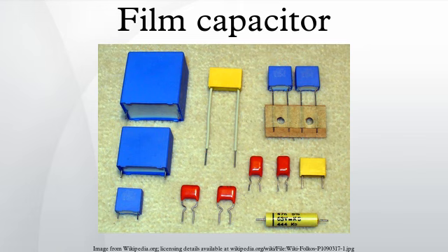The temperature dependence of the capacitance of PPS film capacitors over the entire temperature range is very small compared with other film capacitors. Also, the frequency dependence in the range from 100 Hz to 100 kHz of the capacitance of the PPS film capacitors is plus or minus 0.5%, very low compared with other film capacitors. The dissipation factor of PPS film capacitors is quite small, and the temperature and frequency dependence of the dissipation factor over a wide range is very stable. Only at temperatures above 100 degrees Celsius does the dissipation factor increase to larger values.